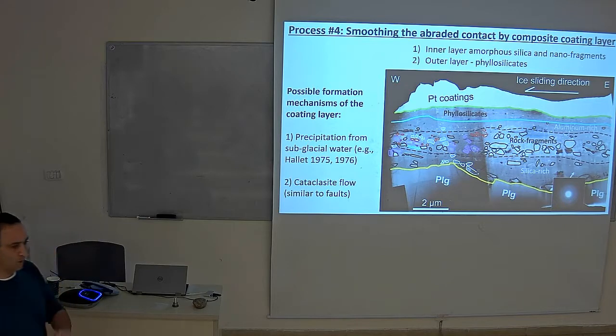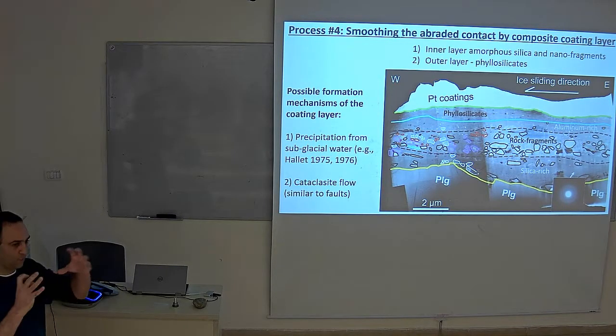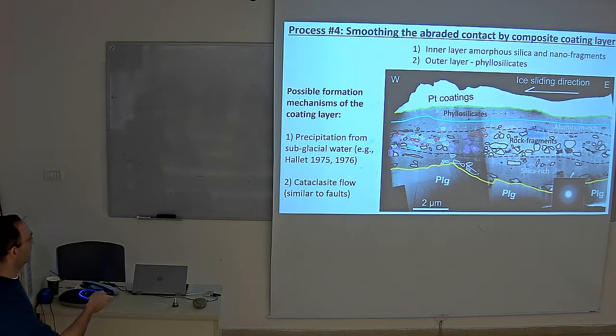What we suggest is also a combination with smearing of the material and adhering it to the surface. And we suggest it especially because of one of the observations, which is this cluster of fragments, where it seems that a particle broke and then it's smeared with the glacial sliding direction, but it's preserved at the same location. So we can see the tail of the small particles, here for the iron oxide, for the K-feldspar, and for the plagioclase. And that will happen if the material is viscous, more like a mud material. So we suggest a cataclastic flow formation, similar to what's happening in faults.